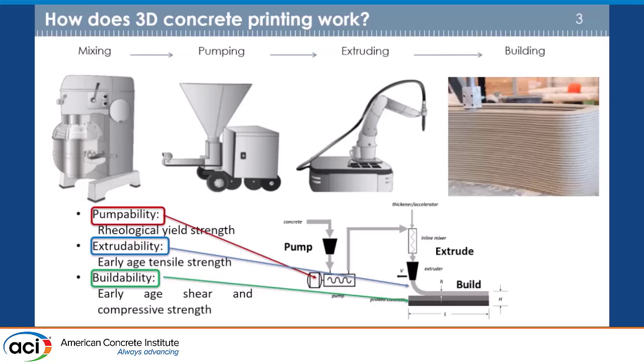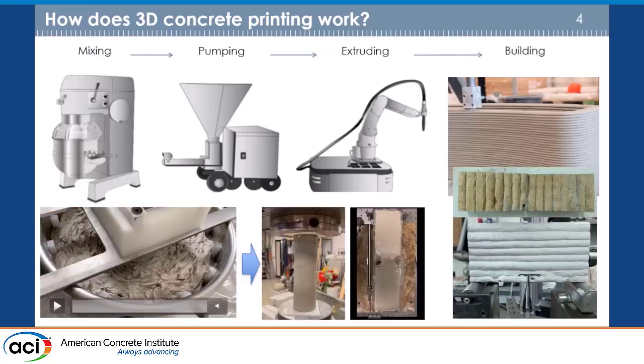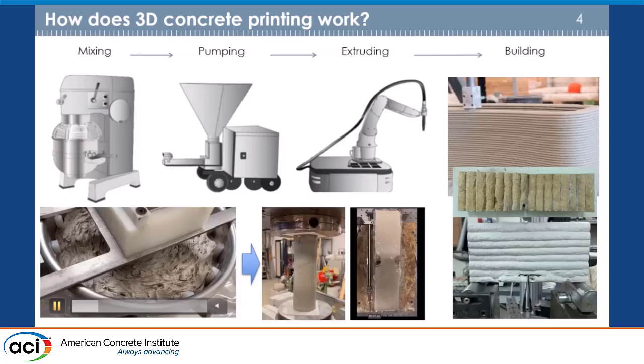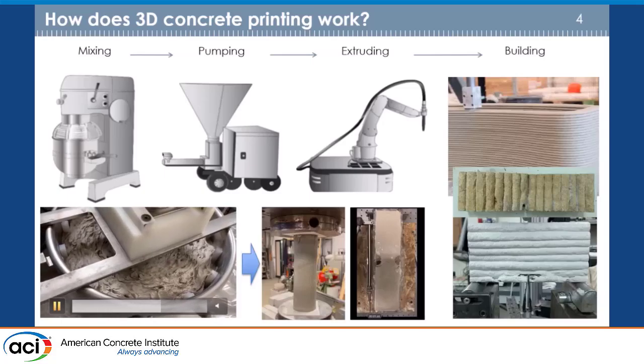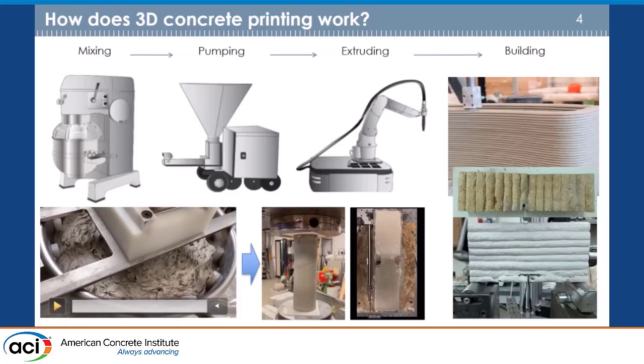Extrudability, in a sense, you can correlate to an early age tensile strength of the material to avoid the tearing off of your filament, and buildability is a development of early age shear strength, but most of all compressive strength and elastic modulus, because you have to cope with the two different mechanisms of collapse, which can be plastic or buckling. And then it comes into play the fact that, for example, when you go to rheology, 3D printing mixes are extremely stiff.